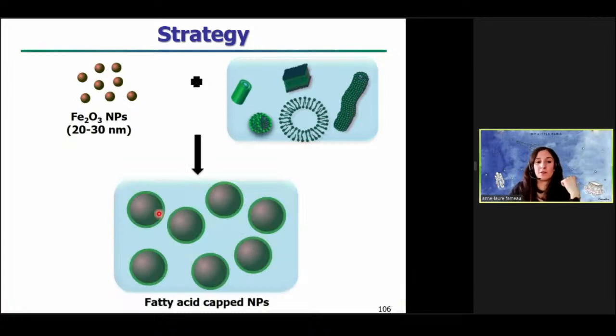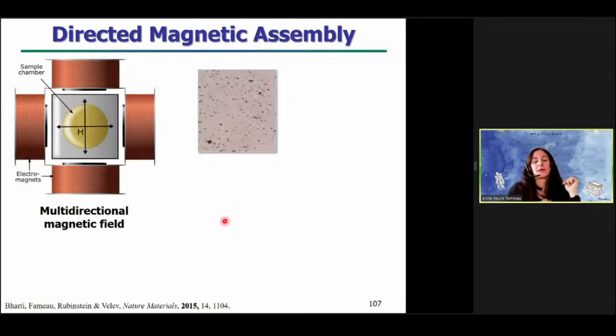So when you just mix the nanoparticles with fatty acid soap, what we observe is the formation of fatty acid capped nanoparticles with a lipid shell surrounding the particles. So then we use a directed magnetic assembly field to produce our filaments. For this, we use a multi-directional magnetic field. As you can see in our setup, it's four electromagnets, and in the middle, you have the sample chamber.